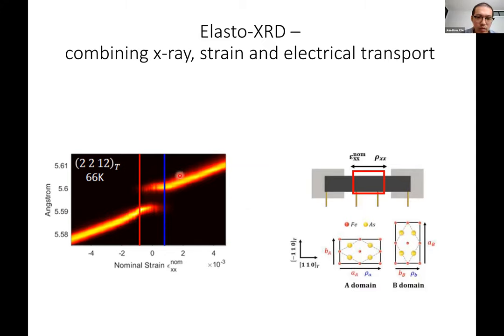So just by looking at this peak, it already answers some of the questions that we had before when we were doing this superconductivity study. For example, we worried that the strain was not very homogeneous. Therefore, for example, the broad transitions might correspond to some part of the sample being heavily strained and the other part of the sample not being strained. But if you look at the X-ray diffraction peak, you can see that the width of this peak is not significantly wider than the width of the peak in the zero strain state. So therefore, in this region of the samples, the strain is quite homogeneous.